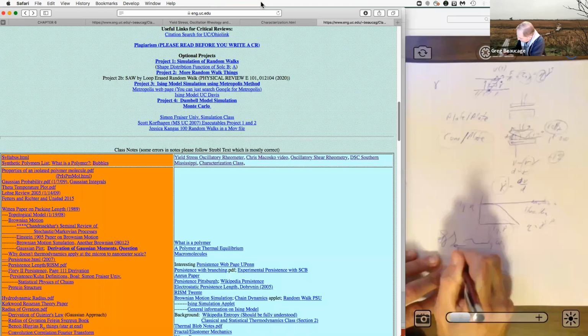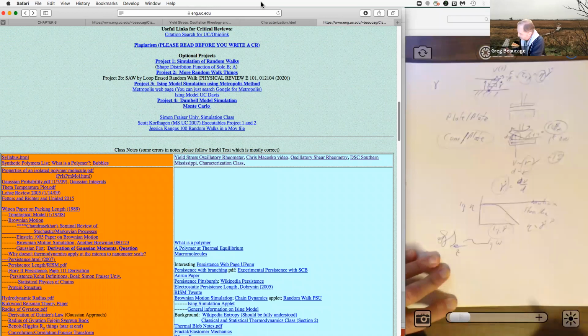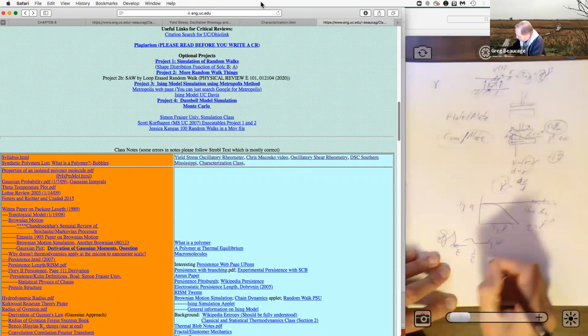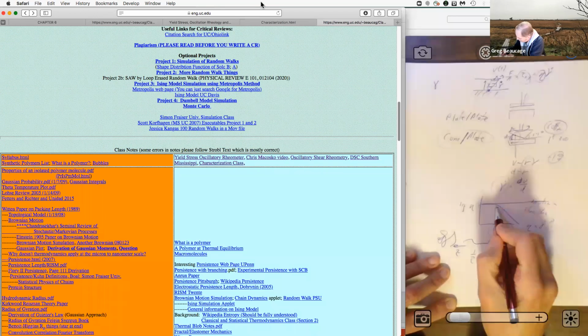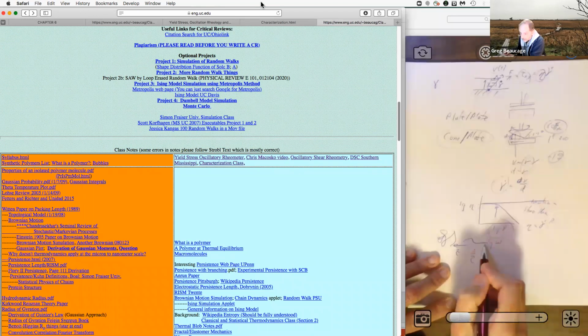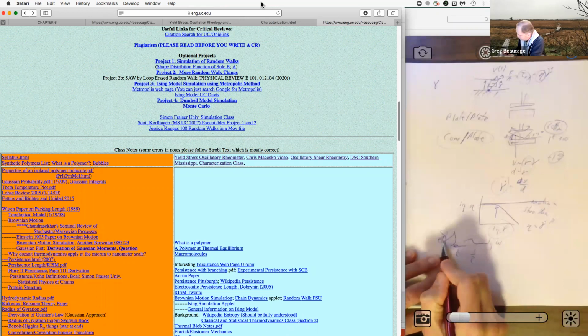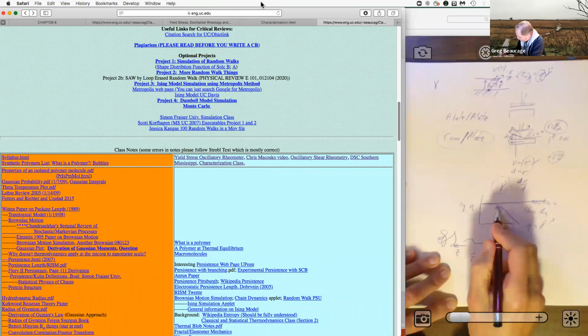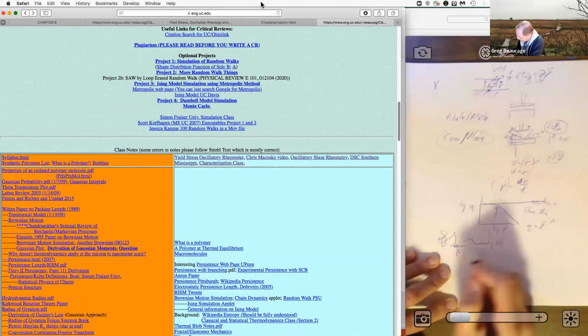That takes a certain amount of time, tau, and 1 over that time tau is going to be this strain rate. Once you're at a strain rate below that, when you deform it, the coil can return, so viscosity doesn't change due to deformation. When you deform it above that frequency, it doesn't have enough time to return, so you've changed the fluid.